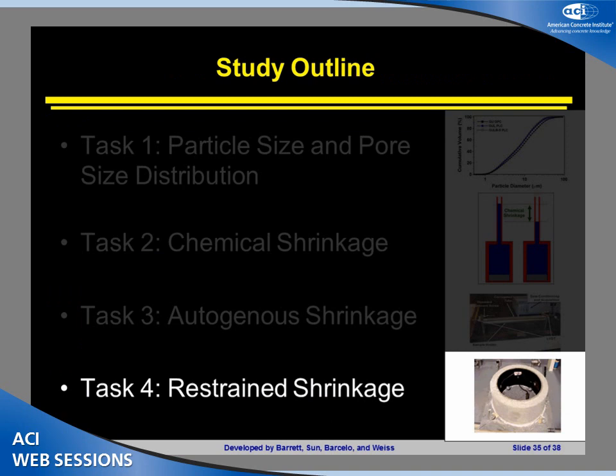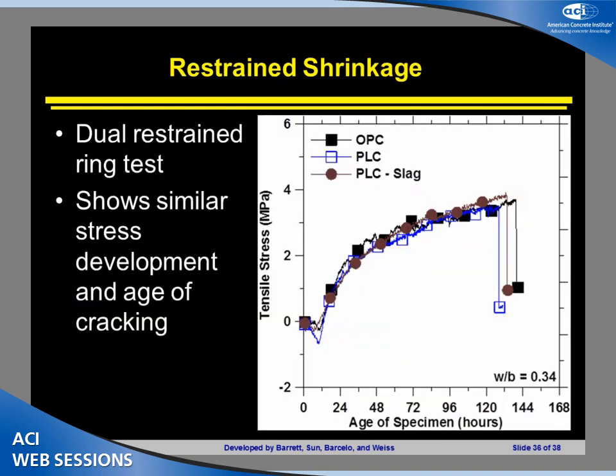If we look at this in terms of restrained shrinkage and cracking potential, again, a similar trend starts to emerge where we say OPC, PLC, PLC slag, and I would argue that it's very difficult to determine anything from this curve other than they really look similar. If somebody wants to get in here and talk about this one cracking an hour ahead of the other one, I'm going to tell you that the variation of that test is more than a couple hours that we're looking at here. So again, the takeaway from this slide is they're very similar systems.